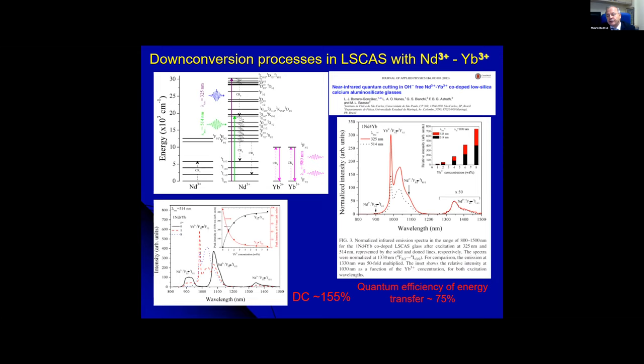the melting procedure of removing the water from the glass, which the water is a very big problem when you get emission in the infrared. So we removed the water, and you can see here, with a sample with 4% doping of ytterbium and 1% of neodymium, we can get this kind of efficiency. It's a very